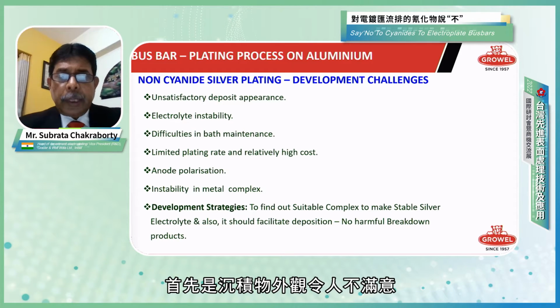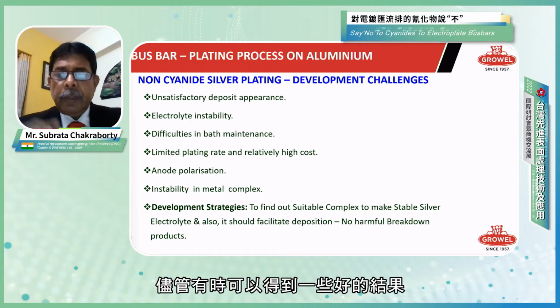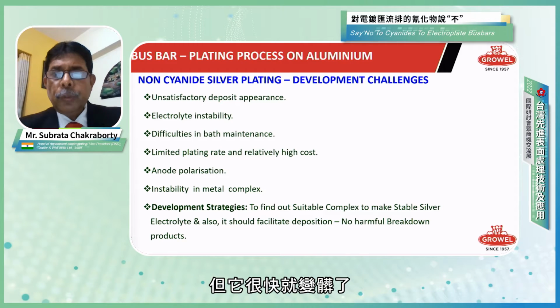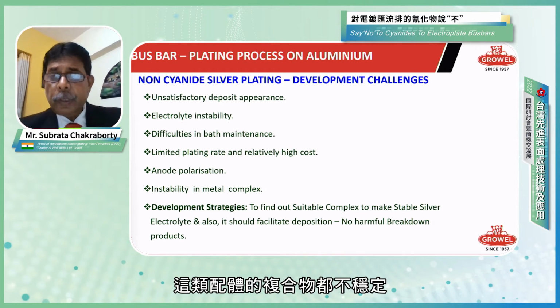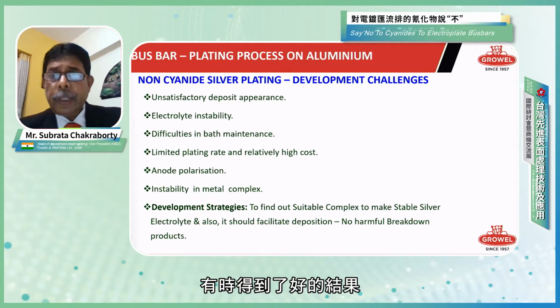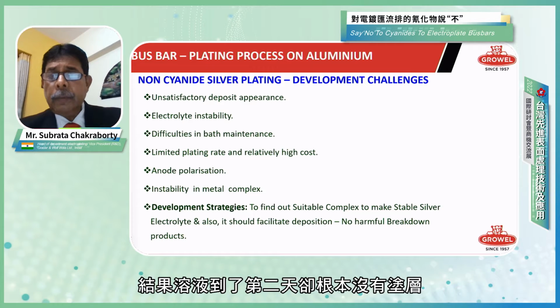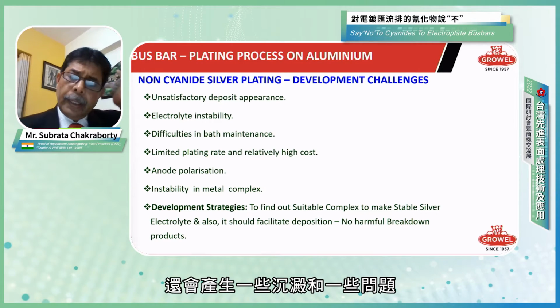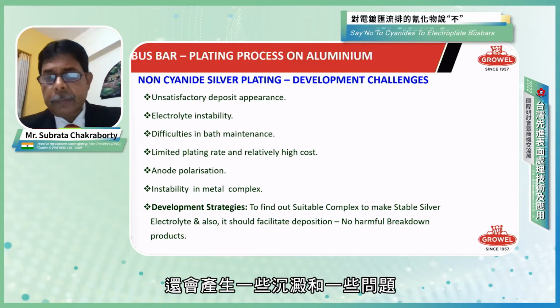First and foremost, the deposits were unsatisfactory in appearance. Even though sometimes we were getting good results, it used to get tarnished within no time. That's not sustainable. Electrolyte stability was not good, because the complex or ligands whatever we tried, it was not stable. Sometimes we got good results, and then the next day no coating at all, yielding to precipitation and other issues.